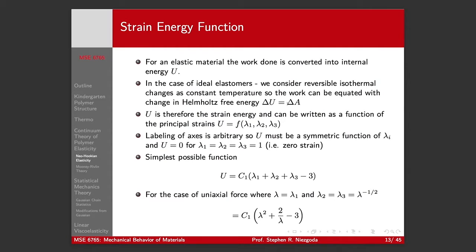So, really, we have a change in Helmholtz free energy. We can think about the change in internal energy as, therefore, the strain energy, which we can write as a function of the principal strains. And the labeling of our axis is arbitrary. So, again, we want this to have material frame indifference. It has to be a symmetric function of our stretch ratios. Meaning, there's no rotation. Rigid body rotations shouldn't give us any strain. That's another way of saying that.